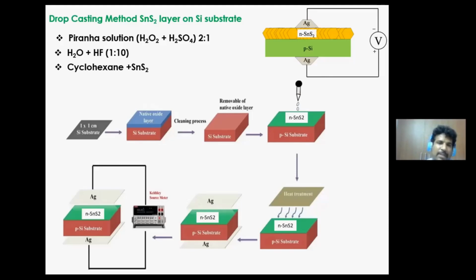With this synthesized material, we fabricated a photodiode. For this, we followed a certain coating procedure. First we chose a silicon substrate. Silicon substrate mostly has a native oxide layer. To remove the native oxide layer, piranha solution and HF solution combinations were used. After cleaning this, we coated this synthesized material, because after synthesizing tin disulfide, we stored those materials in cyclohexane. So we directly used the tin disulfide dispersed in cyclohexane.